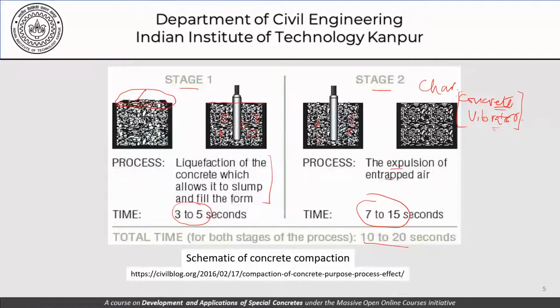So the schematic representation is an in-principle guidance that, so long as we have air continuing to bubble out of the system here, the vibration should be continued. That's something which we can keep in mind and take the actual measurement or the actual description of time with a pinch of salt and move forward.